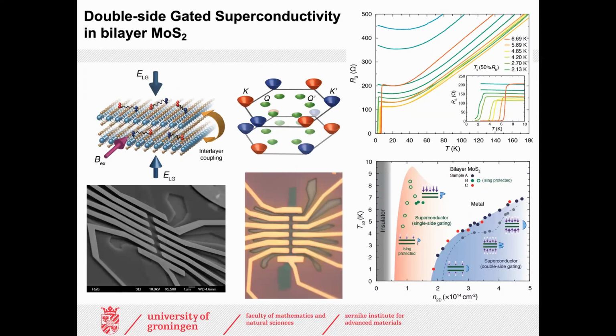So then we go to such a system. Then we can actually see that, yes, we can actually make such a system and gate from both sides. And the effect we are seeing is that compared with the normal phase diagram, the onset of superconductivity actually comes much higher than the onset of the single layer gating. And this onset is actually more than 2 times than a single layer case, indicating some extra pocket is actually present there.